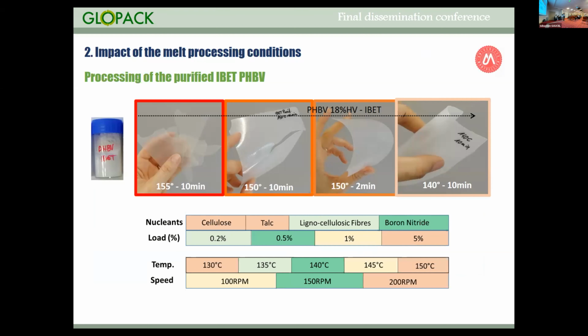And we had a look at the influence of the processing temperature on the mechanical properties, and you can see that depending on the temperature that you use to process the materials, you can have more or less flexible materials. So it's not like PP, where you can have a range of temperature to process the material. Here you can see that within a range of 10 degrees, you can completely change the mechanical behavior of the polymers. So in the project, we determined some optimal conditions to process the grade developed by IBET.